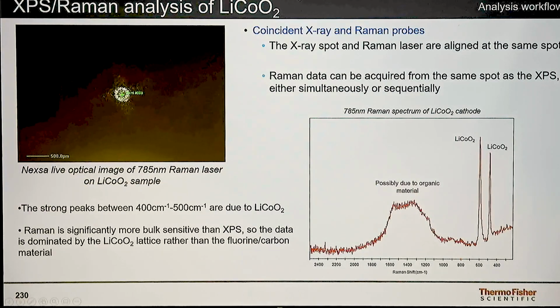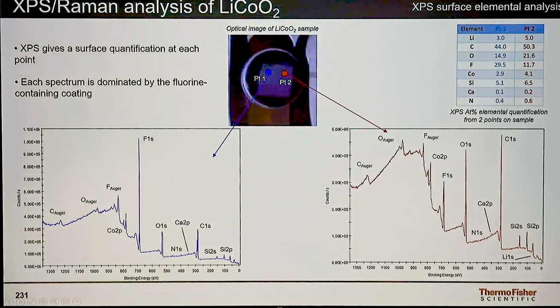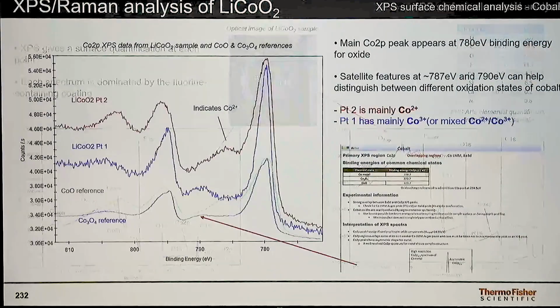If we look with the Raman, so coincident, this is using the 785 laser, so heading towards the infrared, we can see 2 peaks from the lithium cobalt oxide, and then a load of sort of junk basically from the binder material that's there holding the sample together. Comparing with a couple of different positions, though, we can see that there is a bit of variation. So at point 1, lots of fluorine coating. Not so much fluorine here, and we can see variations in the amounts of cobalt and what else? Silicon present in these different points. And we thought it might be quite interesting to compare those.